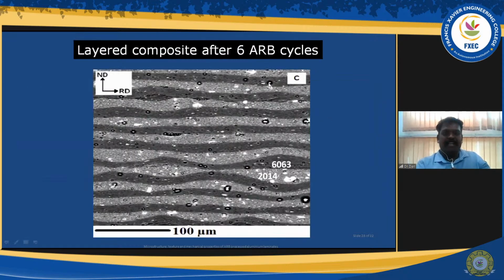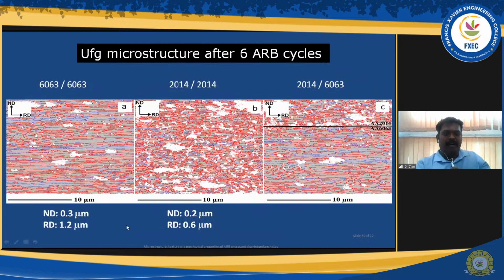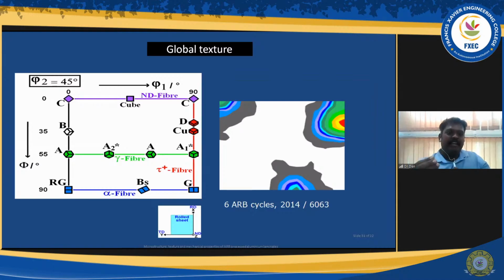You can see they started with coarse grain. Then after 6 ARB cycles, see how the layers look. You can see it's perfectly bonded, right? Two dissimilar metals are very beautifully bonded together here. From the microstructural point of view, it generates very high refinement after 6 ARB cycles. In the ND direction, it is in the range of 0.3 micrometers in one case. In the case of 2014, it is in the range of 0.2 micrometer. And in another case, it is something like 300 nanometer grain size. So they got very significant grain refinement.